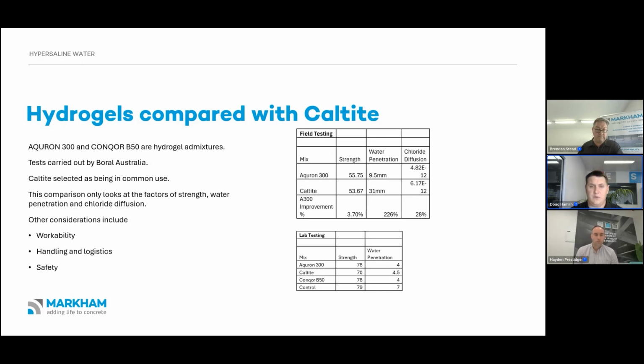Firstly we looked at some field testing, which as you'd all know has some challenges with variability. Concrete testing, that type of thing. But what it did show is even with those sensitive mixes, we were still able to get good results with the Acuron 300 in that example, with some significant improvements both in the water penetration and chloride diffusion. Strengths were much of a muchness there.